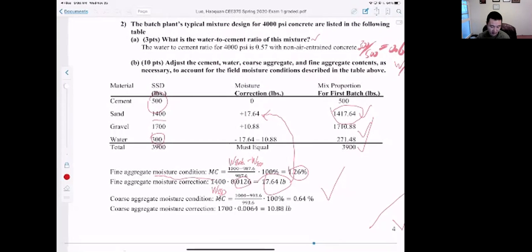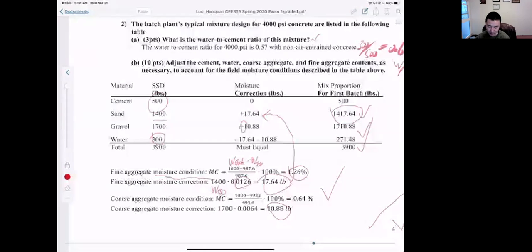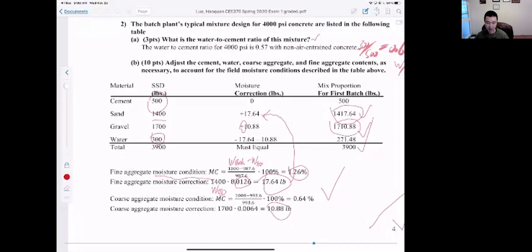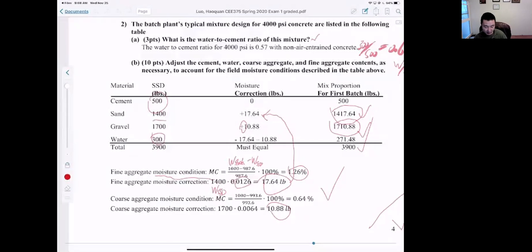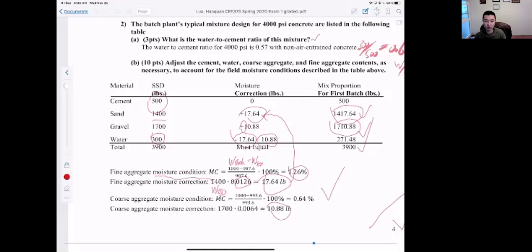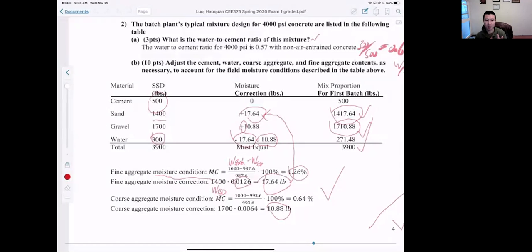Similarly, we can do the moisture correction for the coarse aggregate. This is plus 10.88 pounds, so we need 1710 pounds of gravel. And that moisture will be subtracted from the mixing water, so we make sure the real amount of water in our concrete is exactly 300 pounds. We do not change the water to cement ratio in the system. Again, that's exactly the reason we do the moisture correction. If we change the water to cement ratio, the strength will change. Everything will change, because the water cement ratio is the most important parameter in our concrete mix design.